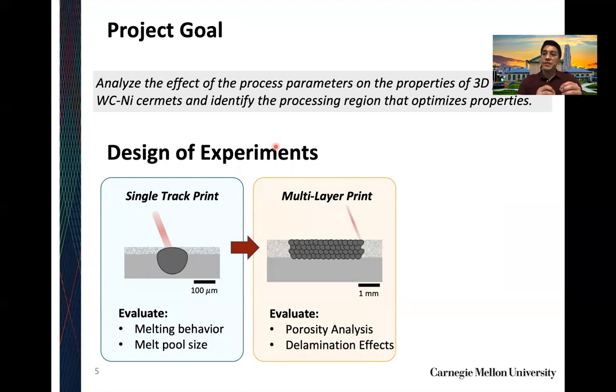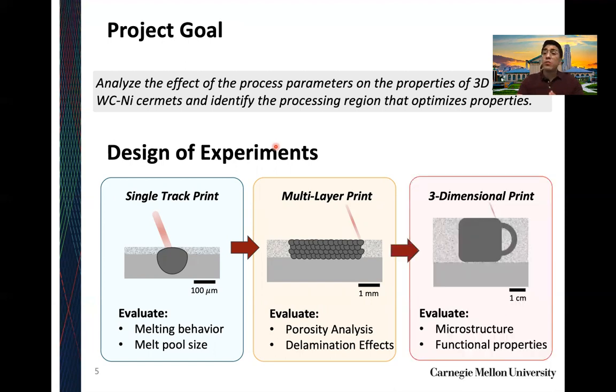Then after that, we leverage those findings to begin building up multi-layer prints. In this case, they're going to be 10 rows or 10 layers worth, about 1 millimeter squares. And there we're going to evaluate the porosity as well as any delamination effects, which are crucial whenever we're working with a new material system. And then from there, we'll leverage those findings to then build a three-dimensional part. In our case, we're just going to build some simple cylinders, and we're going to evaluate the microstructure that results from these process parameters, as well as hardness, the functional property, which is a very important property, at least for tungsten carbide nickel.